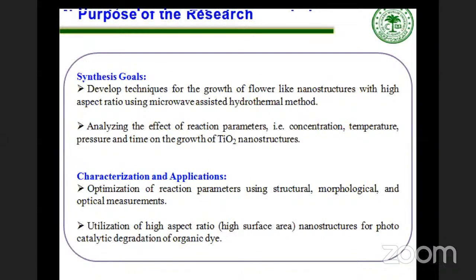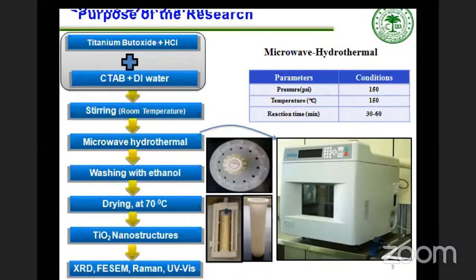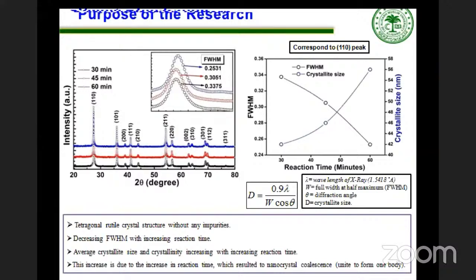We have synthesized these titanium dioxide nanostructures basically for photocatalytic application, and this is the schematic diagram for the synthesis of titanium dioxide nanorods using microwave-assisted hydrothermal method. In the picture we can see the microwave-assisted hydrothermal equipment, and these are the results. First, this is the X-ray diffraction result of our synthesized titanium dioxide nanorods with different reaction times from 30 to 60 minutes. This X-ray diffraction shows that all samples have a tetragonal rutile crystal system without any impurity.